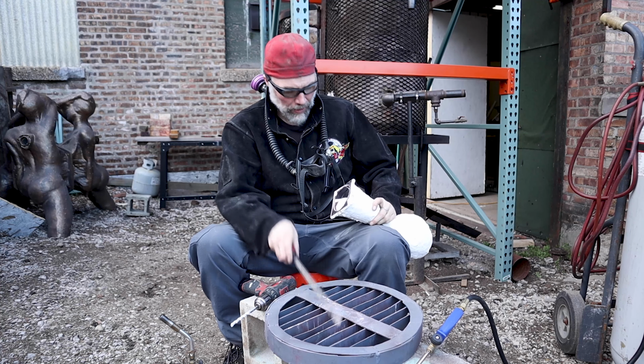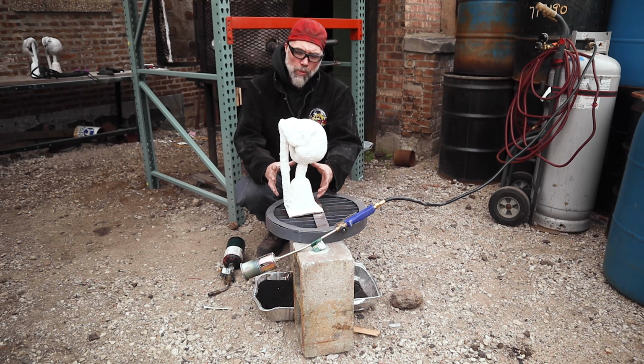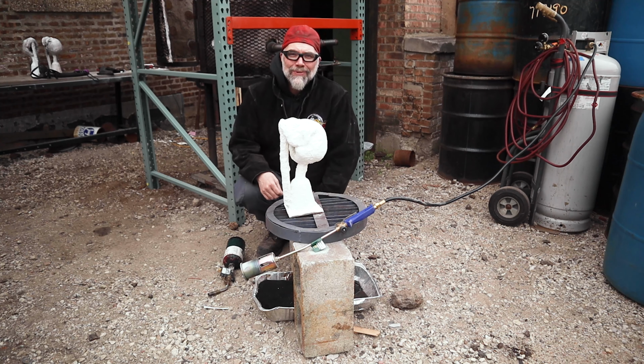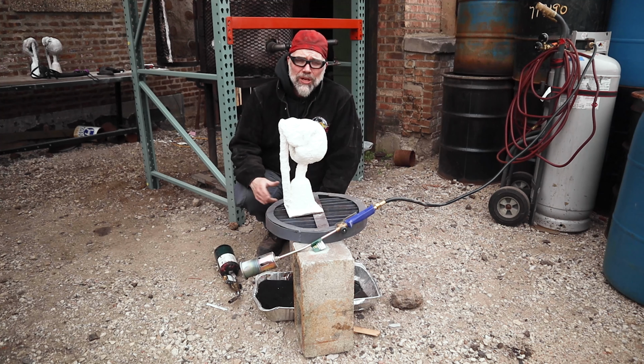I'm going to try to keep the heat relatively low in the cup and the vent and work our way up. And we're going to see what happens, see whether I just blow up the shell, whether it can actually handle it. When I use the hand torch, the limitation is I can get the wax out of the shell, but I can't get the shell as a volume up to vitrification temperatures. I really need a contained environment, either sticking it into an electric kiln once I get the wax out, or you could even stick it in your furnace, depending on the size of the shell and the size of your furnace. You could actually bisque fire or vitrify your shells that way.